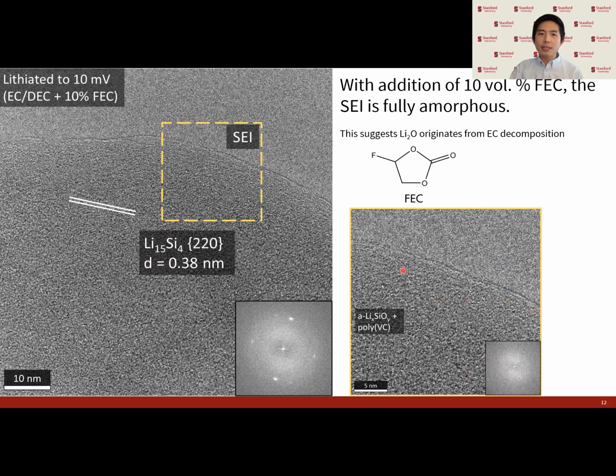FEC is reported to defluorinate during its reduction into a vinylene carbonate radical, along with lithium fluoride. And what we're seeing here is the organic FEC reduction product, which is a polymerized vinylene carbonate along with the amorphous lithium silicate.